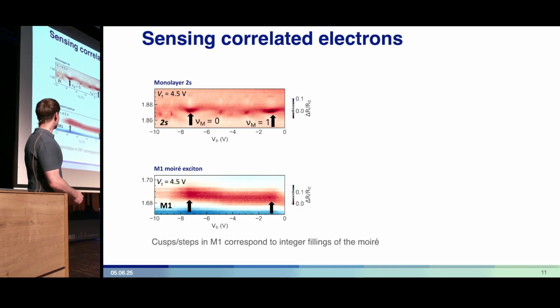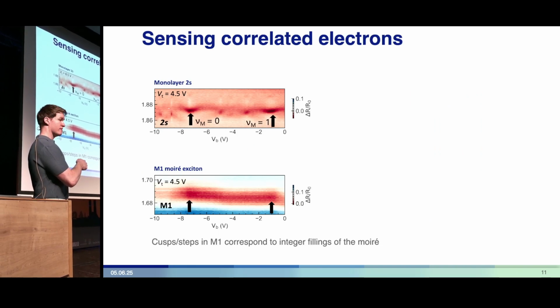Now if we compare what's happening with the 2s exciton with the M1 Moiré exciton, you can see that these discrete cusps in the M1 Moiré exciton line up very nicely with the integer filling insulators detected by the 2s. These cusps and steps seem to be indicating the presence of integer filling insulators in the Moiré itself.